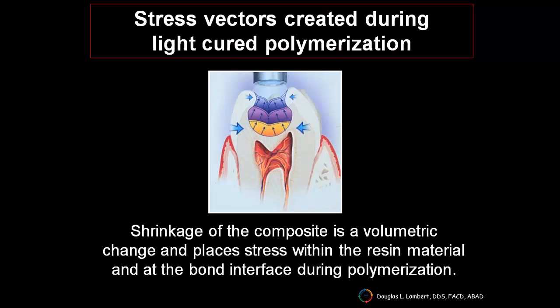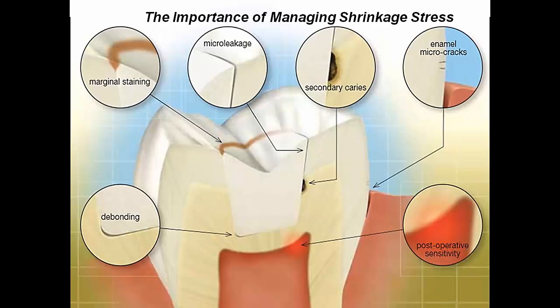Well, we're creating some stress and shrinkage on that composite, and composite's a volumetric change within that resin interface. And there's also a complex series of stresses that occur within the bond of the composite to the tooth as well. The importance of managing shrinkage stress, you can name them off very easily too. Debonding, microleakage, secondary caries, post-op sensitivity, and possibly even enamel microcracks.